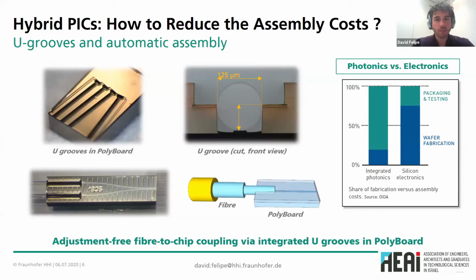And one of the key aspects when we talk about large volumes, and also when we talk about packaging, are these so-called U-grooves that I introduced before, right? So these U-shaped structures on the polymer material allow us to insert the fiber. You can see here, this will be a fiber. This is a cross section of this U-groove. So the fiber can be placed in, and this structure is fabricated by means of etching in a very accurate way, so that the core of the fiber fits the core of the waveguide. So it means that this is kind of a plug and play structure. You plug it in, you don't need to align, and then you have a coupling.